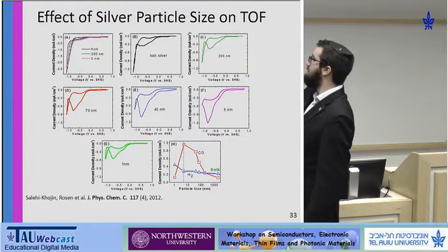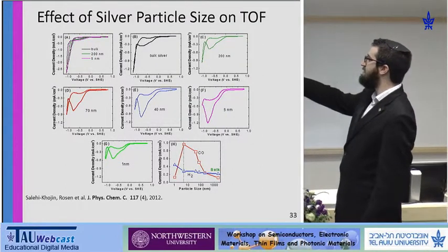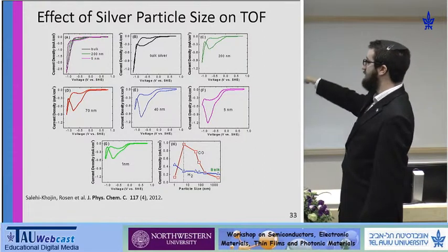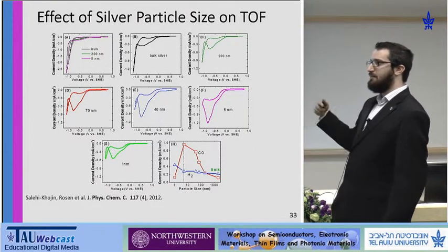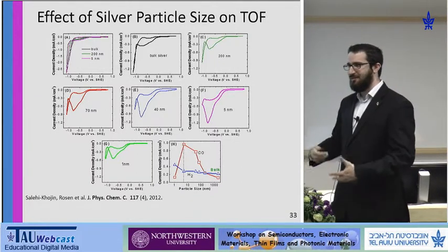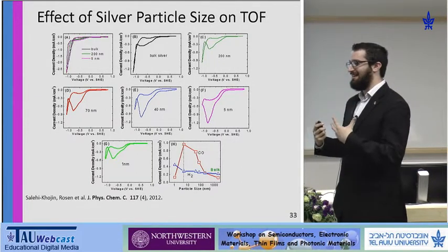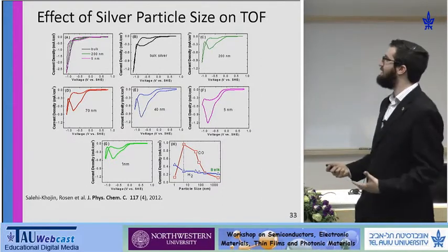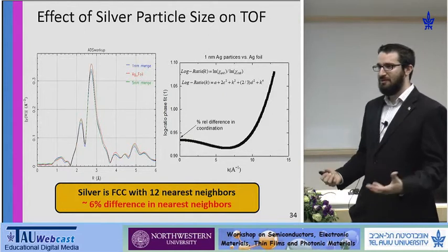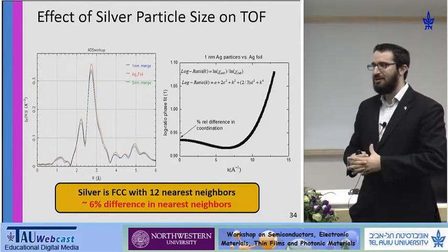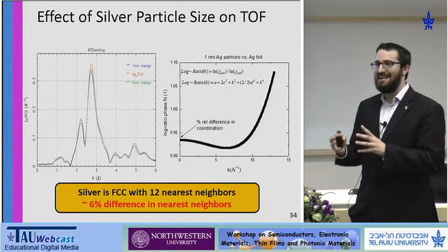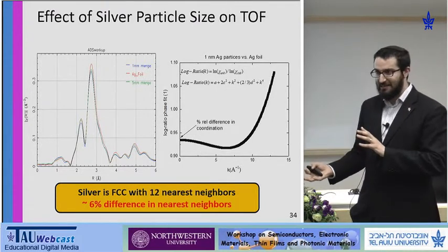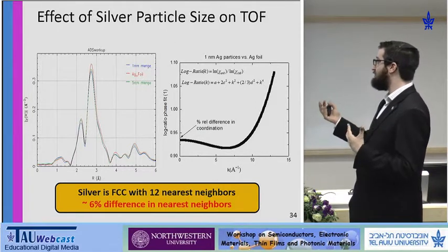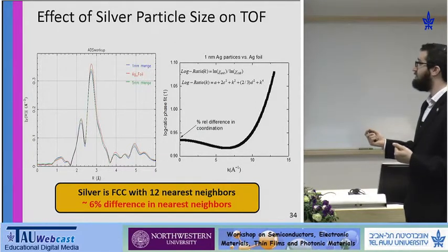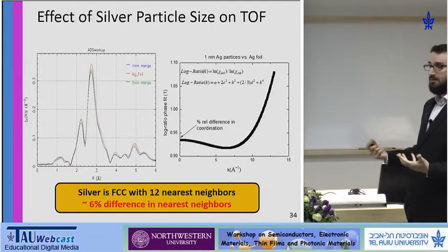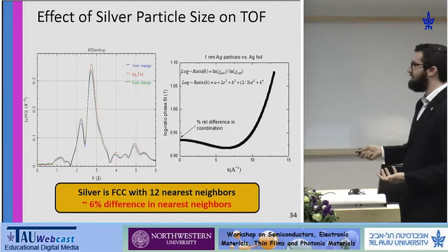So what we saw was a significant increase in the CO2 electroreduction as a function of particle size. Okay, so the question is, it's not just a particle size effect. We wanted to see what was the actual possible cause for it. So we went through the different possible explanations. The first explanation was, as the particle sizes are getting smaller, is it possible that there are lowly coordinated silver atoms that have higher reactivity? And the answer, according to data that we took at Argonne National Lab on their synchrotron, is no. Okay, yeah, so XAFS. So we saw a very small difference.